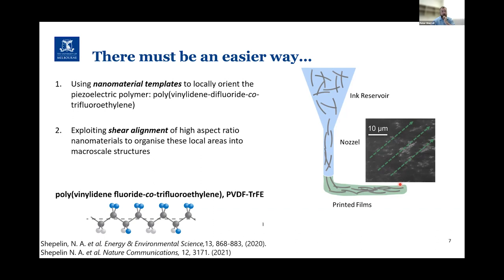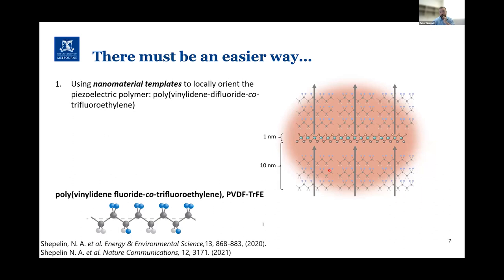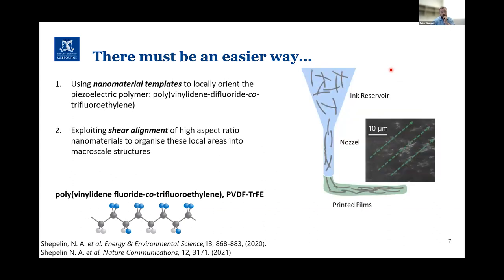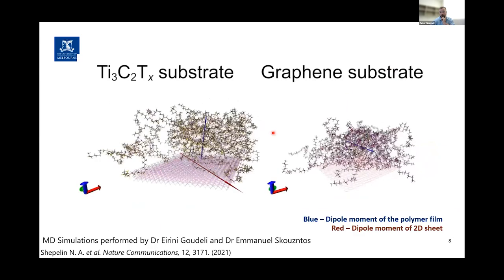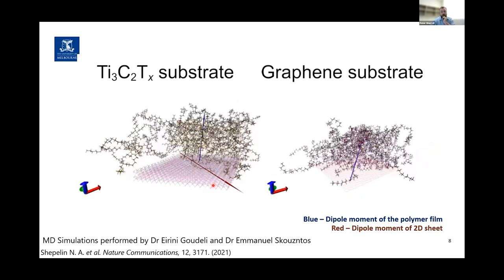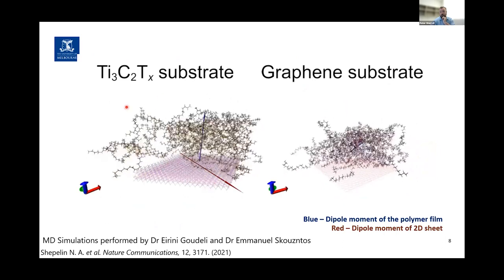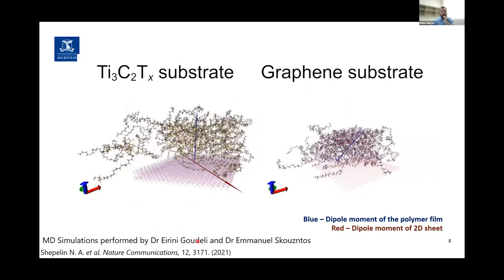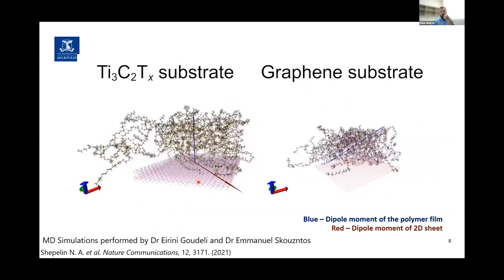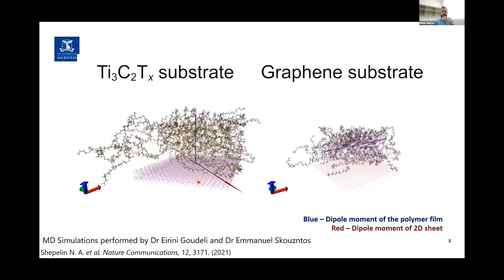So this is all fine, but this is a huge assumption. Why on earth would polymer films assemble with polarization all going in a certain way? Well, it turns out one of the 2D materials we've been working with, which is MXene, is sort of a magical material for this. It has an electrostatic field that goes around the MXene about 10 nanometers above and below the basal plane. What this means is if you drop a polymer with a dipole around it, the polymer will spontaneously orient with respect to that electrostatic field.